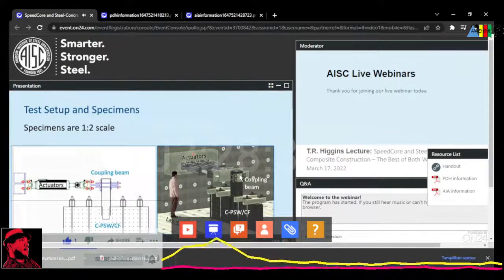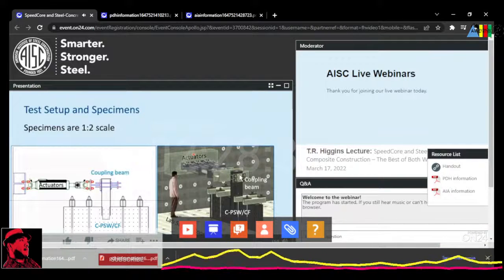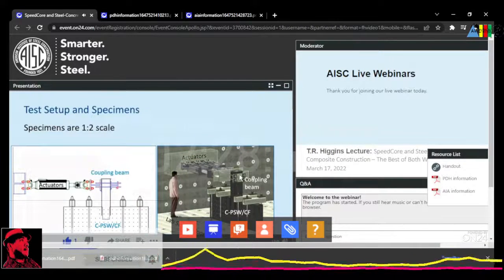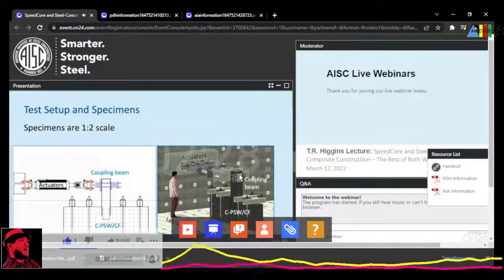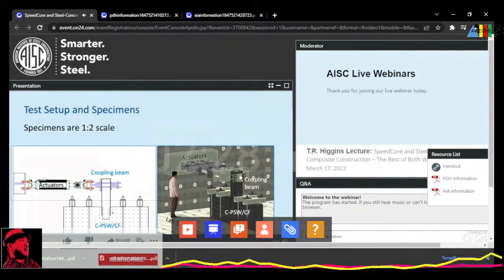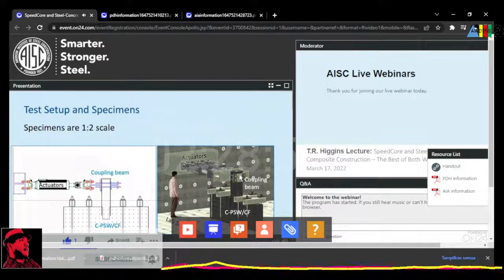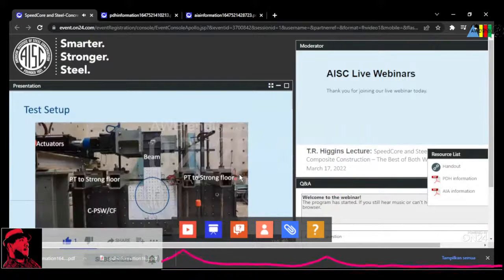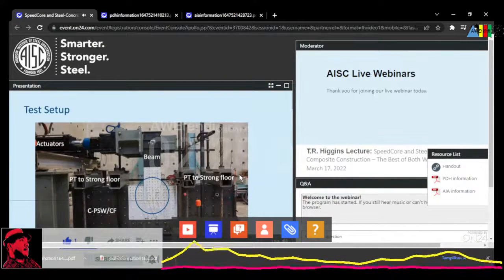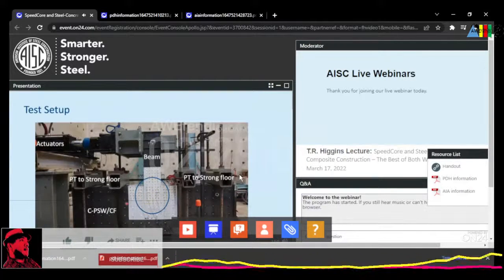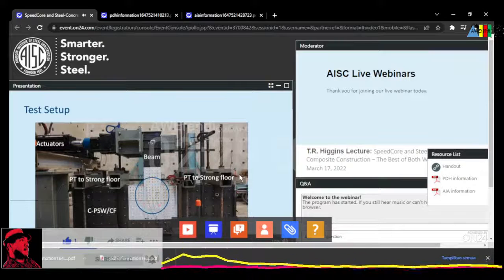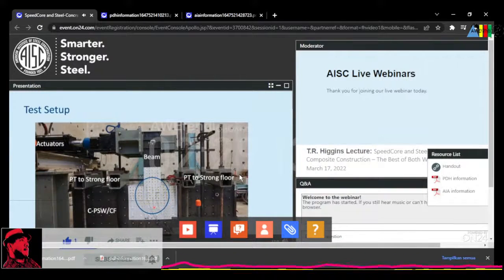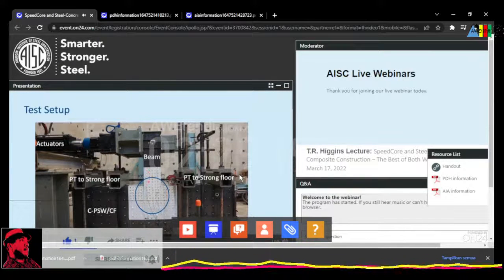The actual test specimens are about 1/2 scale, and the coupling beam to wall connections are tested as shown here. The wall is post-tensioned to the strong floor, and half of the coupling beam height is subjected to cyclic lateral loading according to ATC 24 guidelines to failure using actuators. An actual photograph of the test setup in the lab with all the parts identified is shown here. The connection region was whitewashed and highlighted as shown here. This is connection type 1B with the coupling beam length to depth ratio of 5.